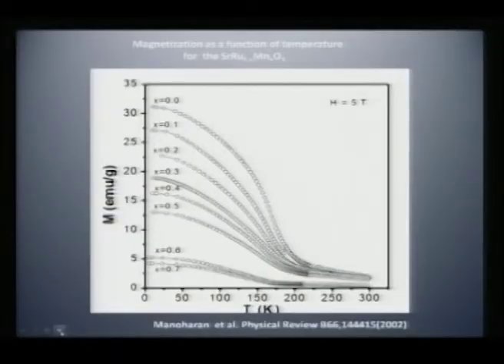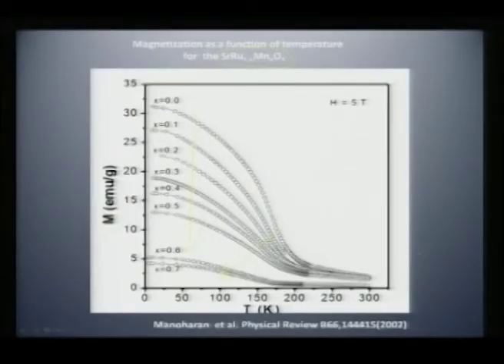So this is a magnetization versus temperature curve for SrRuMnO3, where we systematically keep substituting manganese down the series, and if you plot magnetization versus temperature, you can see there is a strong ferromagnetic loop that is characteristic of these ruthenates, and as a function of this manganese substitution, the ferromagnetism keeps going down. Nevertheless, even at 70% of manganese, you still see a very strong, clear ferromagnetic exchange happening. So why does it happen? Because the end member, SrMnO3, is an antiferromagnetic insulator, but something special should be happening as you substitute.